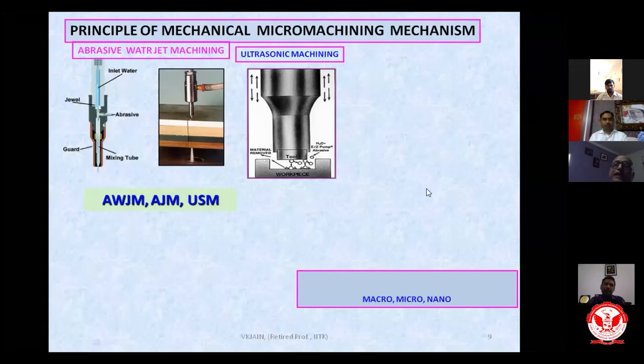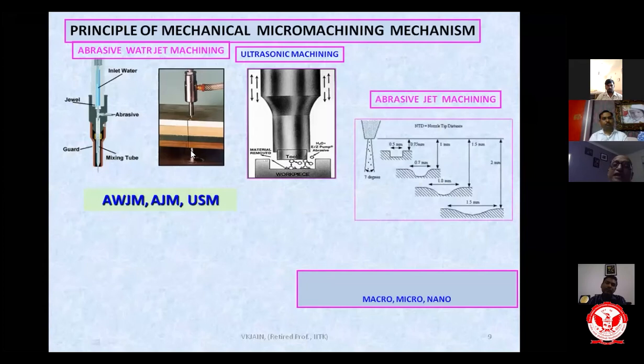Then you have abrasive jet micromachining. Now here you can see the difference. Here you are using water as the carrier medium for abrasive particles, as you can see here. But in this particular case, you are using air as the carrier medium for abrasive particles. Now when the air abrasive jet is coming out of the nozzle, you can see it is diverging. Now the air velocity out of this nozzle bottom is around 200 to 300 meters per second.